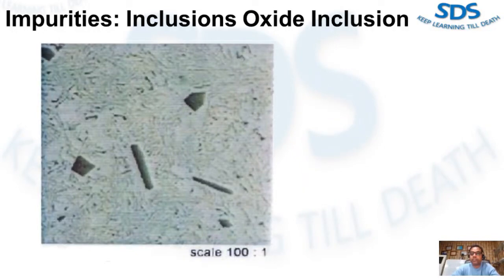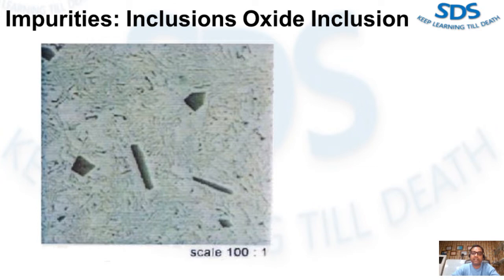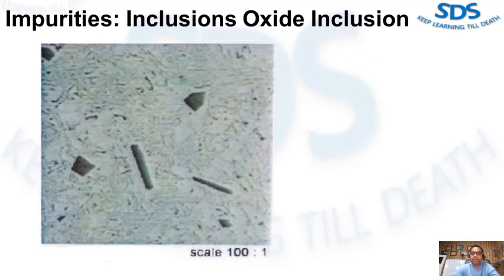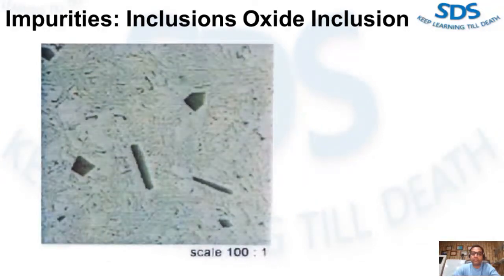When salt fluxes are employed in a fluxing process, these fluxes, which are based on chlorides and fluorides, result in fluxing compound reactions and debris that produce liquid phase inclusions. These are extremely difficult to remove by skimming — they combine readily with the oxide and dross, and the resultant agglomeration is often very similar in density to molten aluminum.